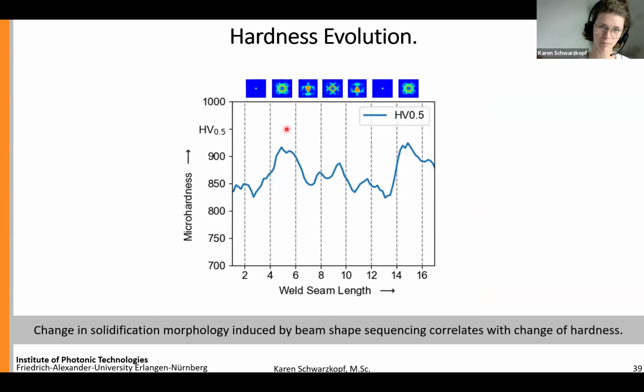As already mentioned, we do see differences in temperature and also microstructure, and therefore we expect differences also in the micro hardness. And this is true. This can be confirmed by a Vickers hardness test with 0.5 load. Basically, what we can see here is that we get lower hardness values for the point and also the triangular shapes, and higher hardness levels for the square and the ring shape. Since this is done on single track experiments, we have to interpret these results with caution. But I think what is really becoming clear is that we are able to see differences in the micro hardness depending on our beam shape.